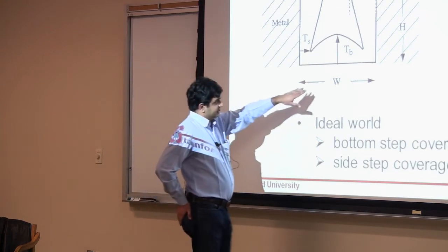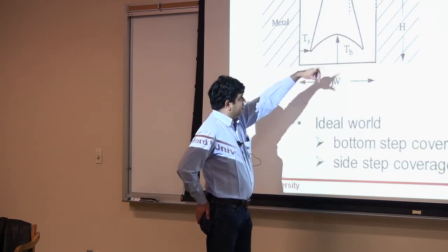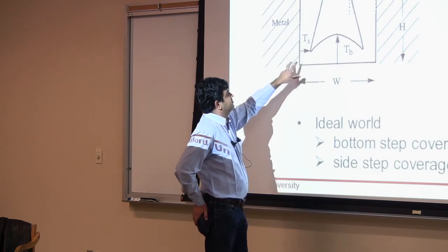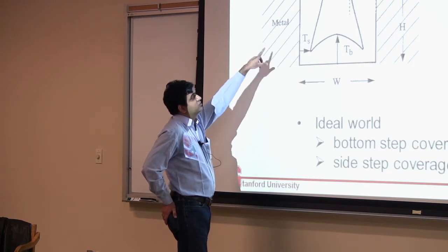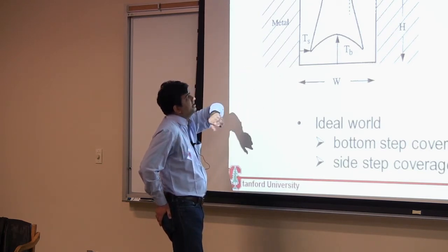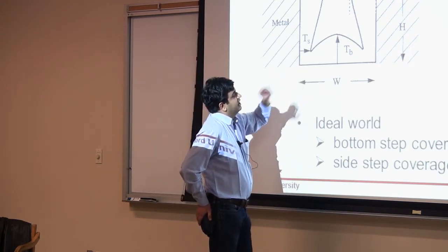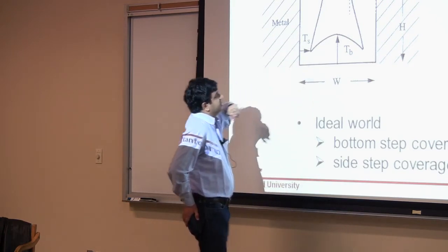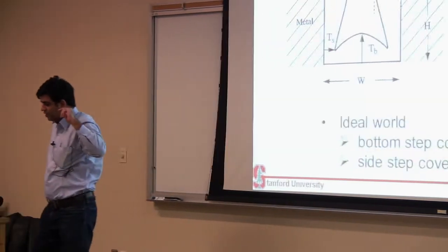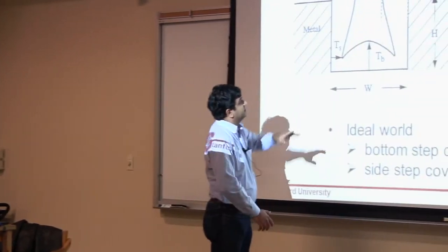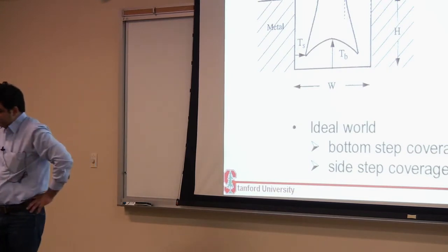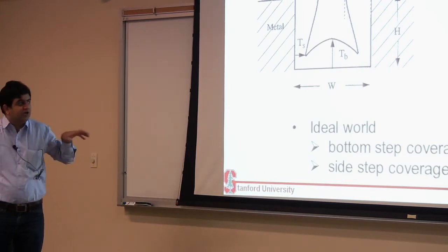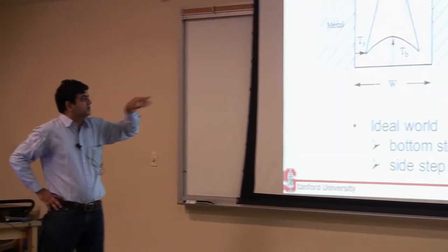Especially when you have dielectrics and you're depositing liner materials on them. If you are doing a back end of the line process, you have a mold of silicon oxide and you want to deposit maybe a tantalum nitride barrier. You would want it to be very thin, a nanometer thin, and very conformal, right? So that's a problem. This is showing something which has an aspect ratio of maybe 1, but in reality I have aspect ratios of 60, and I want to deposit very thin liner materials, or fill them with a dielectric without causing a void.